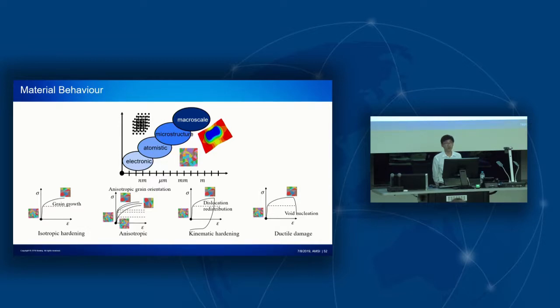So all material behavior we observe can be a result of the microstructure evolution. And the microstructure evolution is a result of atom interaction. So material modeling is indeed a multi-scale problem. In this talk, I will just briefly talk about four very important material behaviors for the sheet metal forming process. They are isotropic hardening due to the growth of the grain, and then the anisotropic plasticity due to the non-uniform grain distribution, and kinematic hardening due to the redistribution of the grain dislocation caused by the secondary loading. And lastly, the ductile damage is caused by the nucleation of the void.